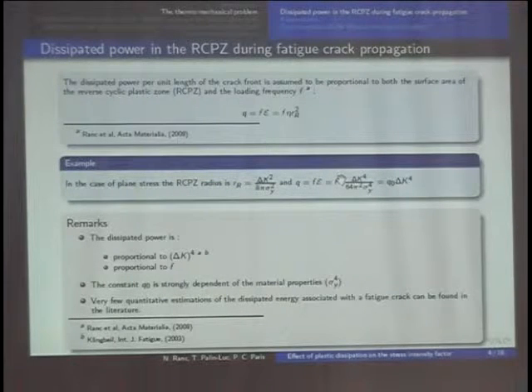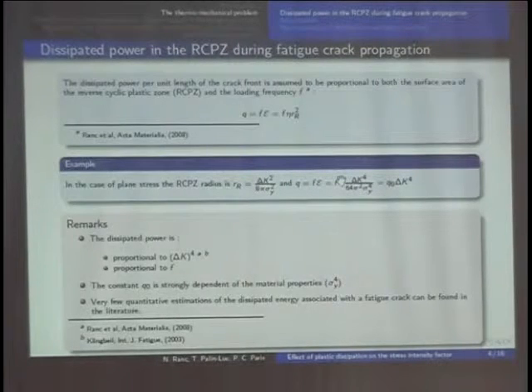In the literature, many people focused on the dissipation in heat of plasticity for very fast cracks, for instance during impact loading or during quasi-static loading, but only a few papers, according to me and my colleagues, focus on what happens under cyclic loading. For instance, my colleague Nicolas Ranc proposed in 2008, based on experiments, that the dissipated power per unit length of the crack front is proportional to the radius of the reverse cyclic plastic zone to the power 2, and proportional also to the loading frequency.